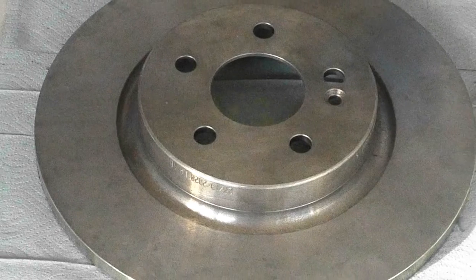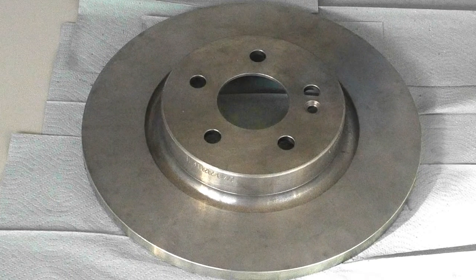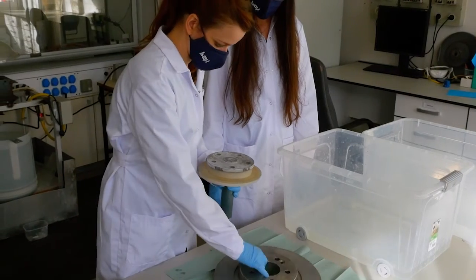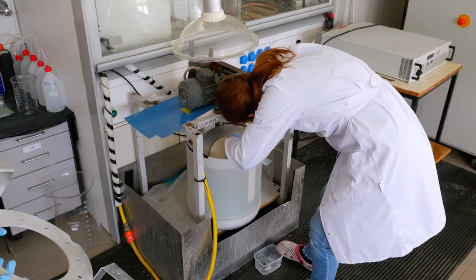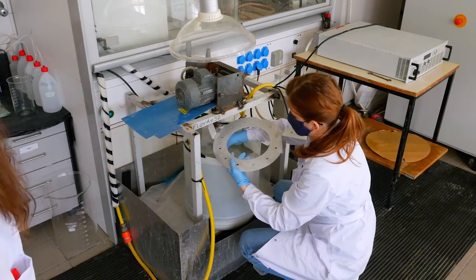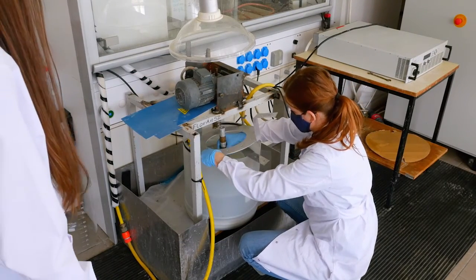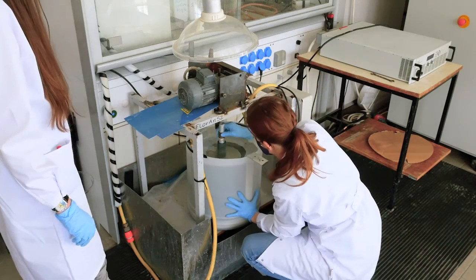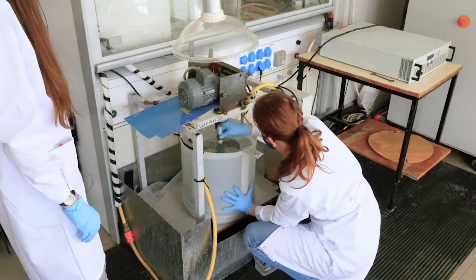The next step in our work was to upscale the coating technology and work on real brake discs. We created an anodizing equipment for this special task. The disc goes on a rod with which it is immersed in the electrolyte. The end of the rod is attached to a rotating motor. The rotation of the disc is necessary so we can get an even coating.